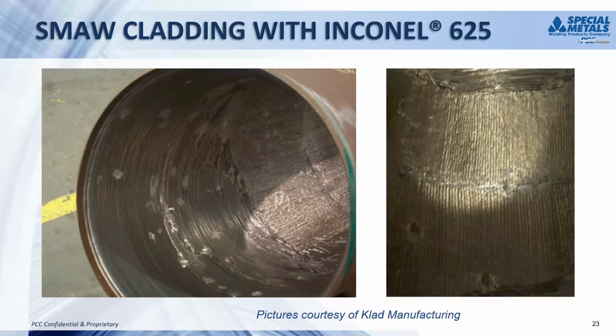So if you were putting in a lot of heat and going quick, you'd probably deform that, and you'd end up with some kind of not round shape by the time you're done with it. So just the nature of the shielded metal being a slower process allows that to hold its shape a little better, and allows you to clad on a thinner surface than you could with some of these other processes we'll talk about in a little bit.